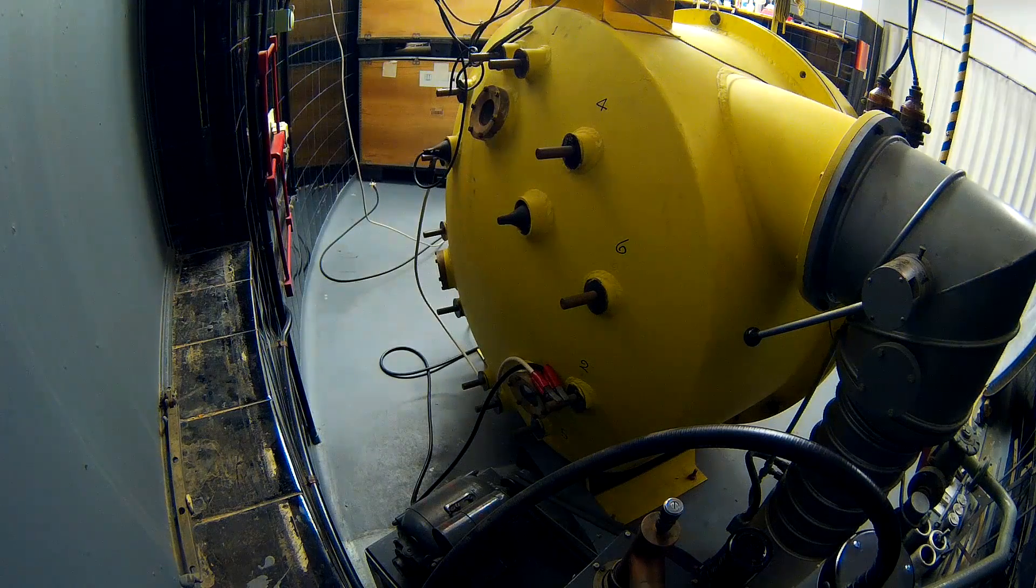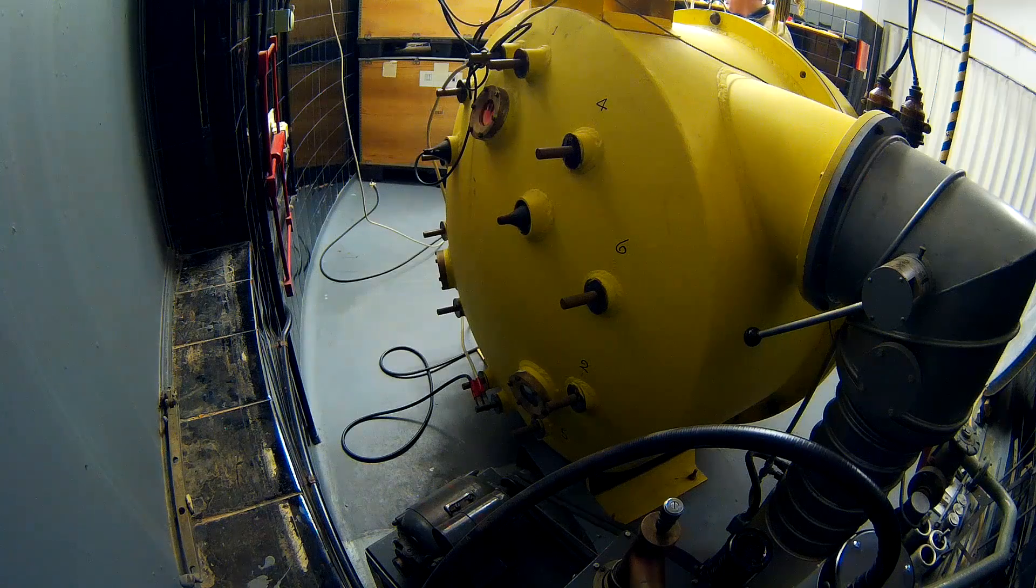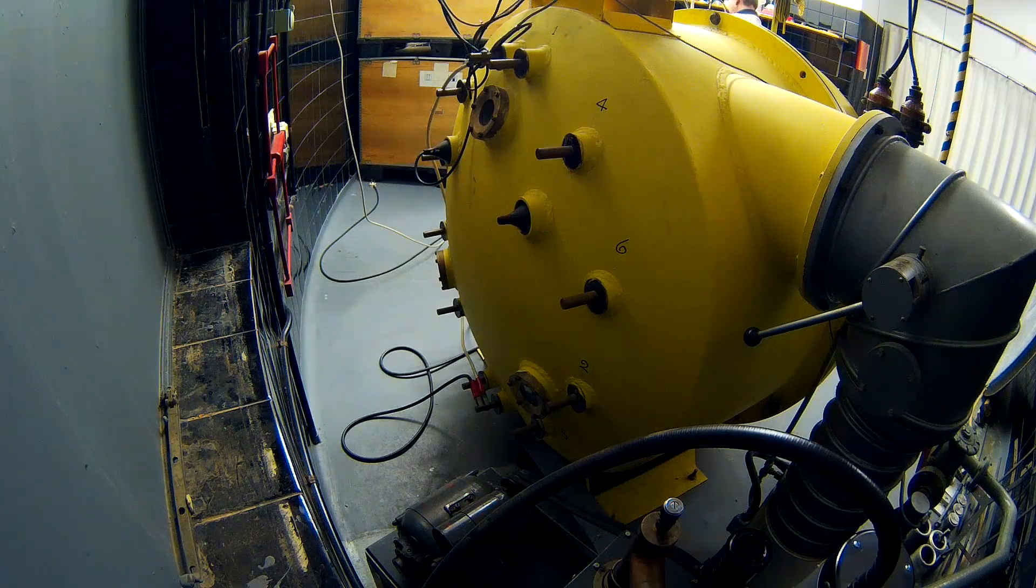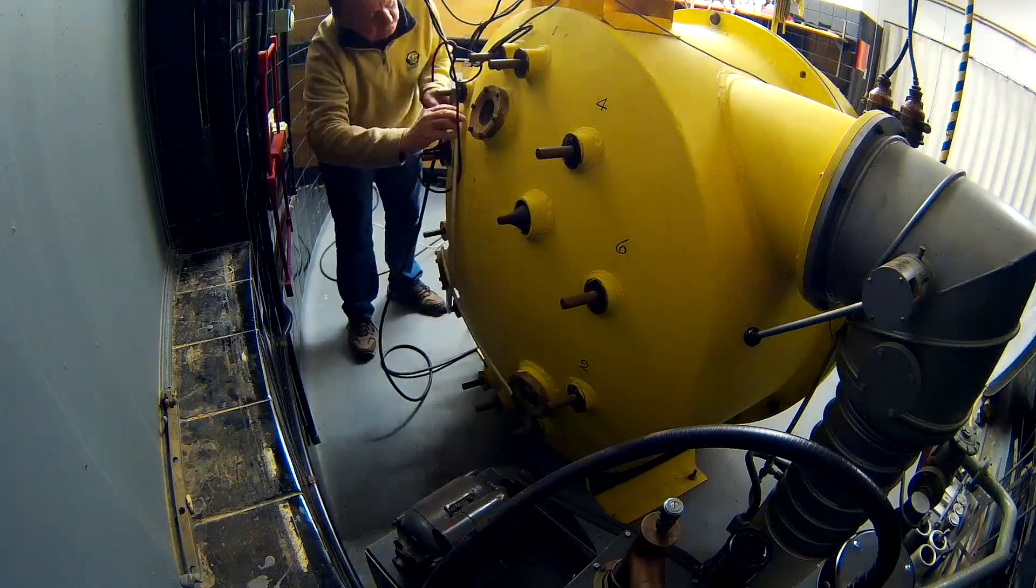The 12 tungsten coils inside the tank are fired two at a time by changing connections at the back of the tank. Their glow can be seen in a small porthole at the back. Notice a double pulse each time - the aluminum melts and cools down the coil slightly. It looks even better with the lights dimmed.